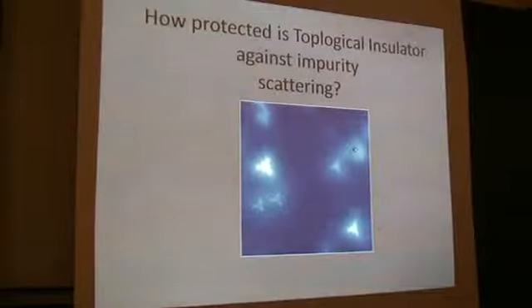If there is a bulk gap, and if your impurity is non-magnetic, I would say the general theory says that it's impossible to generate low energy surface states, unless you break time reversal invariance, or you need to close the bulk gap. Yeah, I basically agree with the statement in general, but this is exactly where I'm going. I will argue that if we have enough scattering locally, that will engage the states outside your Dirac cone, then you don't have to respect time reversal. You form the bound state or quasi-bound state.